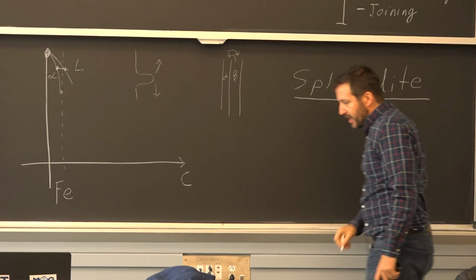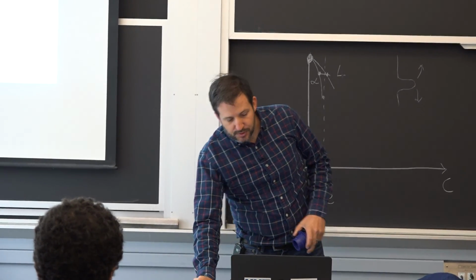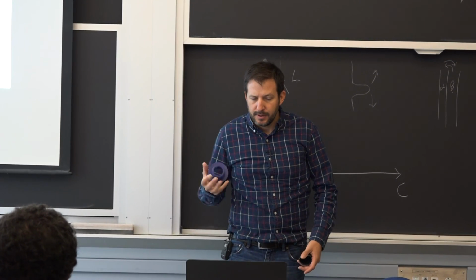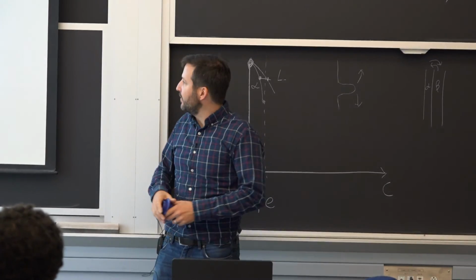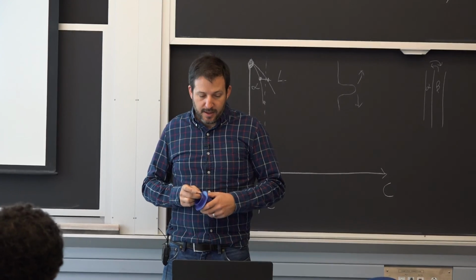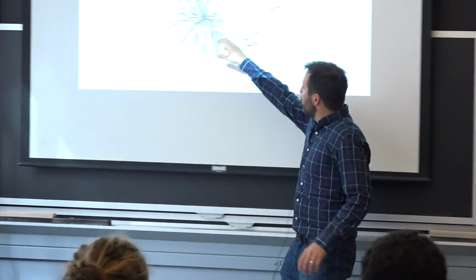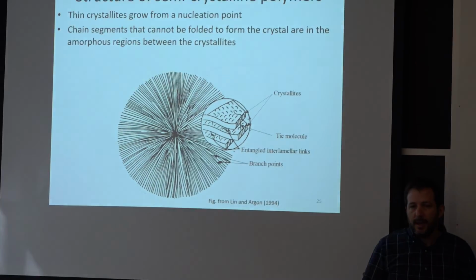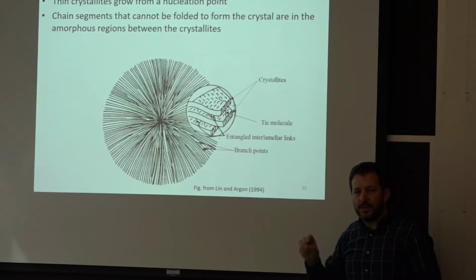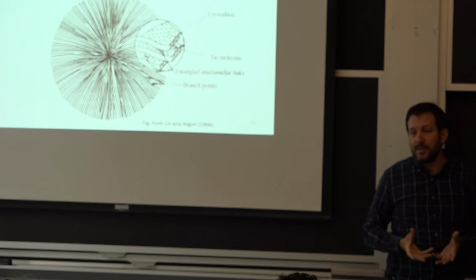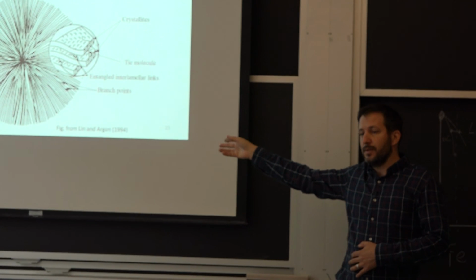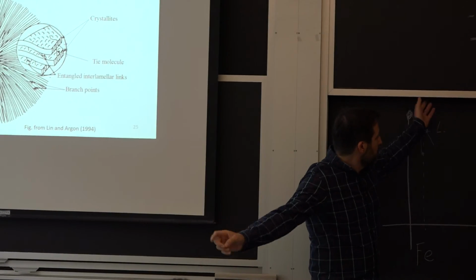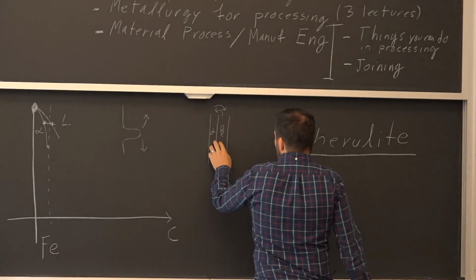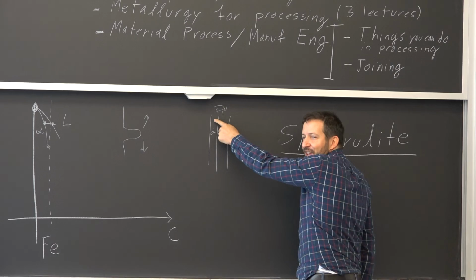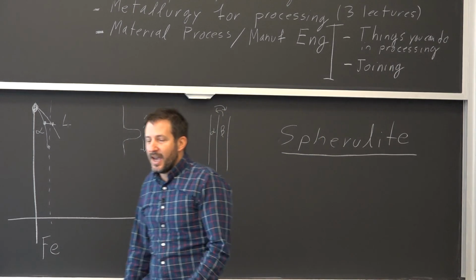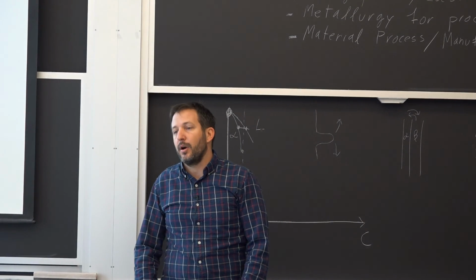These are about the same size, so it's micrometers in size, and as opposed to the metals, you have a lot more of these nuclei forming in the center of the part at the mid-wall. What happens is you start from the very center, you start forming an arrangement, so you fold that molecule into a crystal shape, and then it grows from there, and eventually it merges with the next one. So it's just little assemblies, because it's not crystals, there's thousands of crystals in each one. And the idea is a little bit like we were talking about here, where there are two things. You say, I'm going to set aside what is disorganized and take what I can organize, and that's how you form those crystallites. They have a lot of implications for the quality of a part.